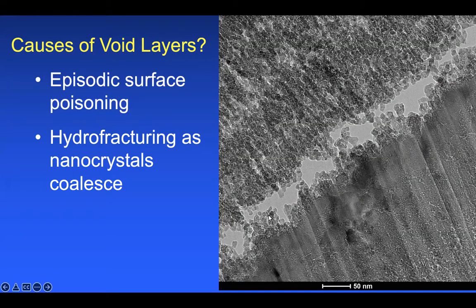And then if there's another episode of rain, and so further growth of the iron oxyhydroxide, only some of these crystals are really going to be compatible with additional growth. And so we end up with this kind of a void layer. And so right now that is my best guess as to what's responsible for the growth of these voids. Another possibility is that we know when these nanoparticles are coalescing, they have to be releasing water. And so I've also wondered whether there isn't an inclusion of water during the buildup of these successive layers as they grow. That might be a part of the story as well.